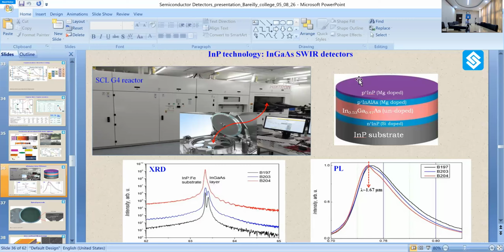This is a typical layer structure which is used for near infrared to shortwave infrared detectors. Okay, so as I already mentioned, this is the indium gallium arsenide active layer grown on the indium phosphide substrate. This is basically the layer structure. This is basically a photodiode. You can see this is a P-type material. This is an I layer, PIN. Okay, this is basically a PN diode, and an intrinsic layer is sandwiched between the P plus and N plus, so I can enhance my absorption. Okay, so the absorber layer is basically indium gallium arsenide, with a particular composition of indium.